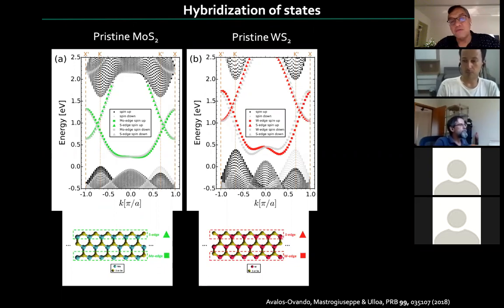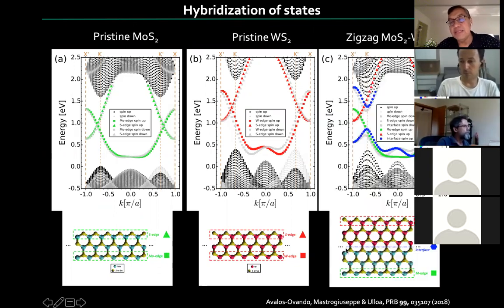So now when you make the interface, you can imagine that the states that are nearby will get distorted. So you'll have the outer edges, which will remain basically untouched, this green and red. But the interface now has one state on each side of this ribbon, and in fact they hybridize. They gap each other because they see each other. The electrons are tunneling back and forth. And you end up with these blue dispersion bands. Again, there are always two of them in gray.